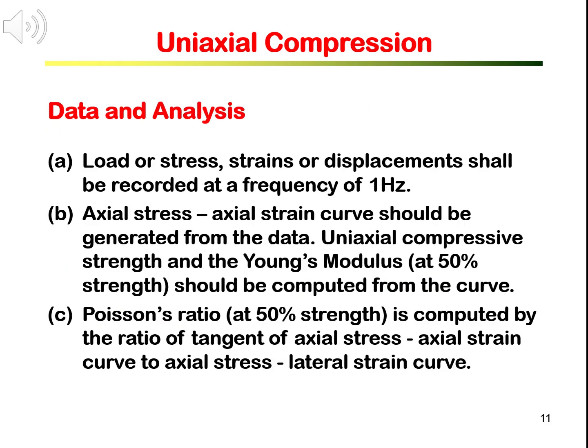As we mentioned earlier, during the test, measurements on load or stress, axial and lateral strains or displacements are recorded at a frequency of 1 Hz by the computer data recording system. The computer will easily generate the axial stress, axial strain curve from the recorded data. You can ask the computer to produce a linear curve through the data regression, which will make the curve easier to see and analyze. You can get the uniaxial compressive strength and the Young's modulus from this axial stress axial strain curve.